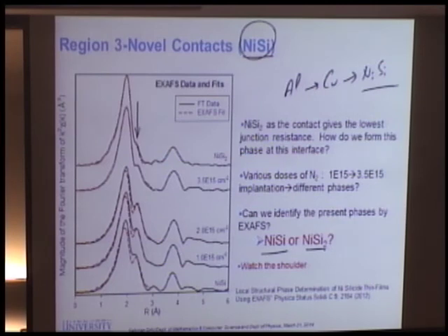And we did the XAFS analysis on that. I saw this funny feature. You see that peak is scaling with some part. What they do is process their nickel silicide with different doses. At some doses, you get that feature. At some doses, you don't. And we looked at that shoulder, did the analysis, and tried to get the X contribution and 1 minus X contribution of these samples.